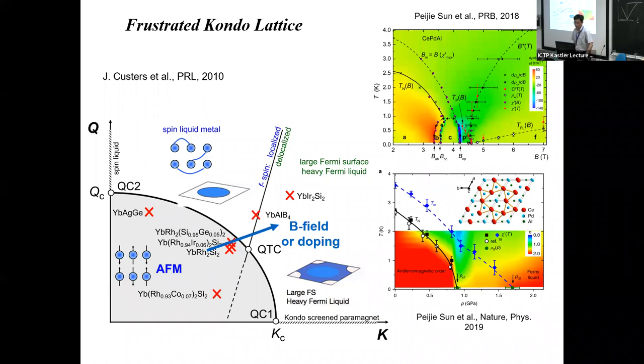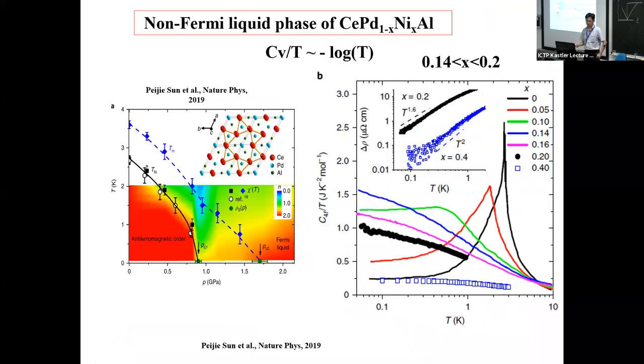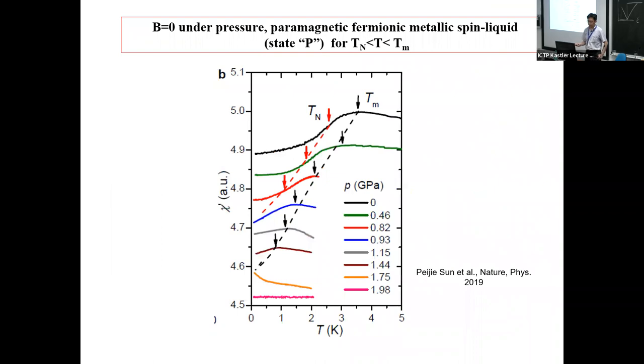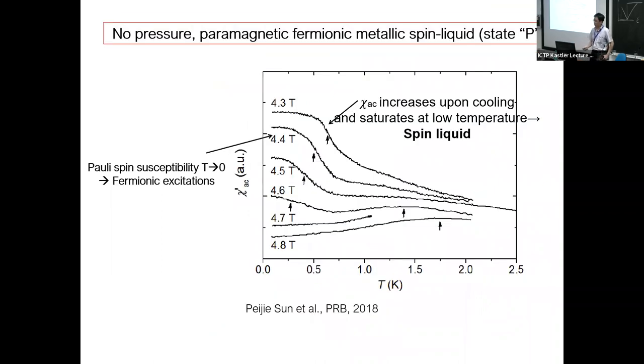Yes. Phenomenologically, how do we distinguish the quantum spin liquid phase from the paramagnet? Neither of them has long-range magnetic order, and therefore both have vanishing AC spin susceptibility. So good question. Thank you. Remember, this AC spin susceptibility for spin liquids doesn't shoot up as Q is raised, as in a paramagnetic material. It's saturated. It doesn't go down to zero either. So it's saturated at a finite value. This is the indication of spin-liquid-like behavior. Of course, it has other possibilities, but this clearly distinguishes them.